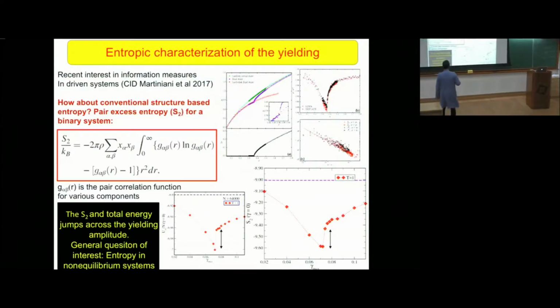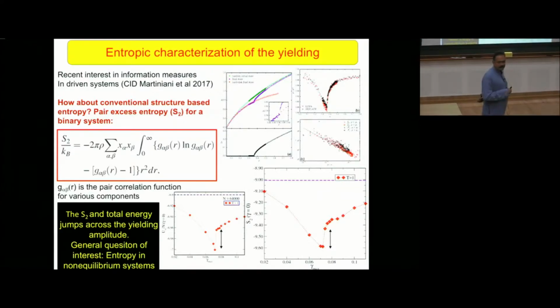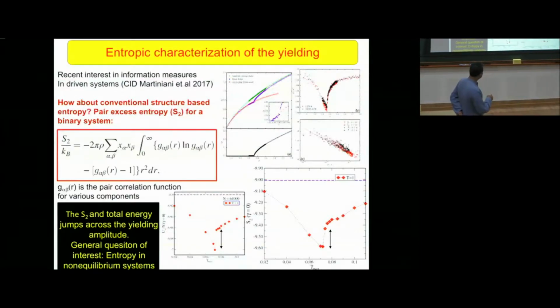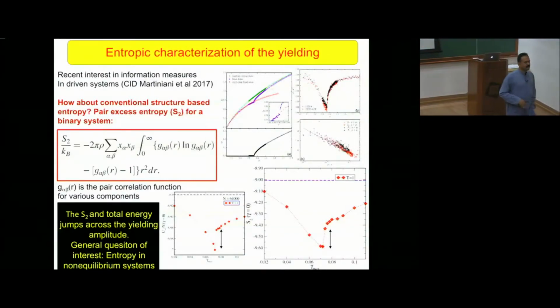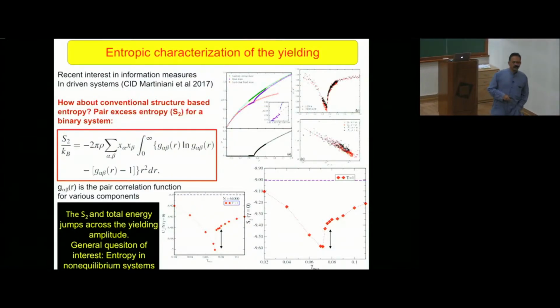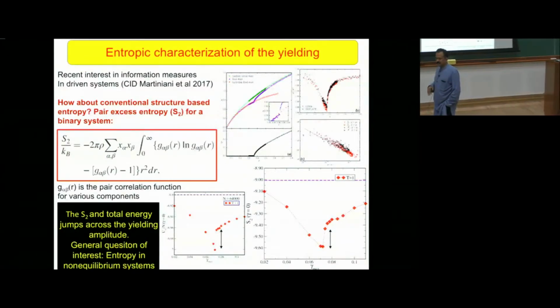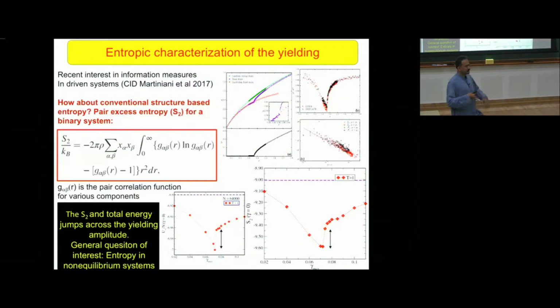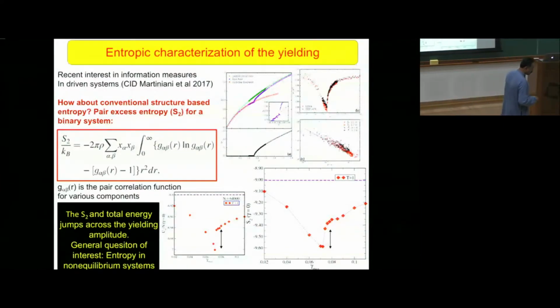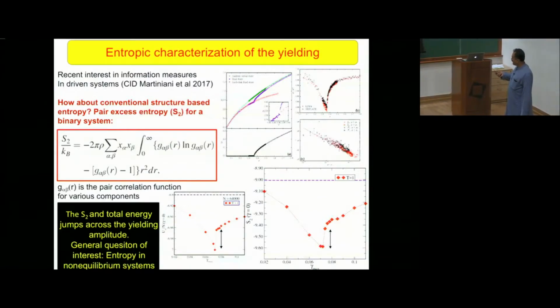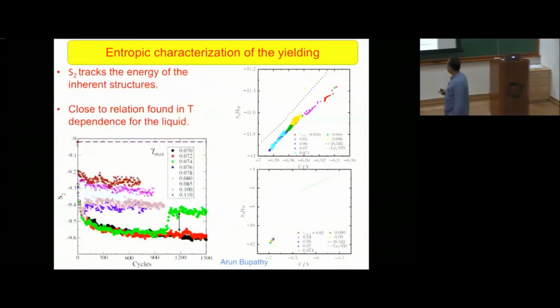Okay, so there's been a lot of interest in looking at the information content of non-equilibrium systems. You heard some of you, Dov Levin's lectures on this, and these are figures from his work with Stefano Martiniani and company. But this approach of computing the information density as a measure of entropy so far doesn't work so well for continuous systems. While we're trying to understand it, we said, why don't we look at other measures of structure-based entropies, such as the pair correlation entropy, which is a standard quantity that you study in liquid state theory. And indeed, that entropy does seem to capture quite crisply the fact that you're undergoing a transition at the yielding point. I won't say more.